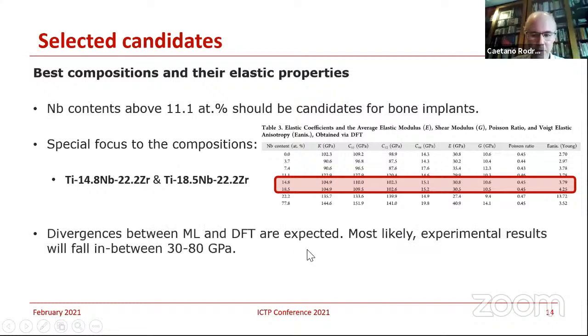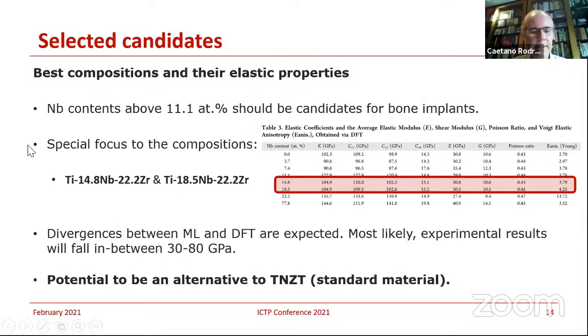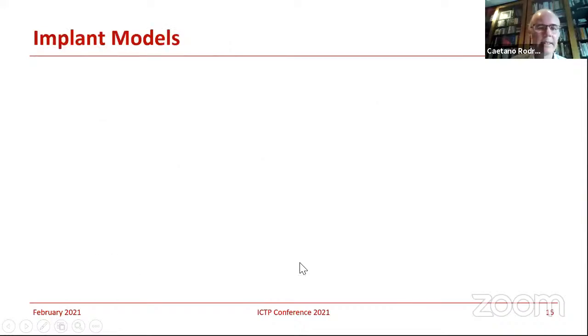And finally, of course, you have some differences between the machine learning and the density functional theory. This is expected, but they still are in good shape compared with the experimental part. So this means that these compositions can be a potential alternative for TNZT as a standard material. Now, this is very interesting because in the end, you could figure out a nice composition that gives us good elastic properties. Now, to the end, then you have applied that for implant models.